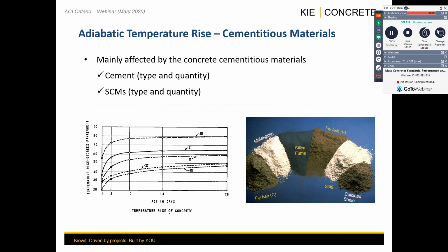So like I mentioned, adiabatic temperature rise is going to be mainly affected by the cementitious materials, the composition, the amount. More cement, obviously, is going to cause the material to generate higher heat. Use of Class F fly ash, in the case of Ontario, is not available, but in the case of slag, it's available. So you can use slag, and you can use low heat cementitious materials to compensate for the heat that you need to meet in thermal control plans for mass concrete. So make sure that you understand temperature rise.